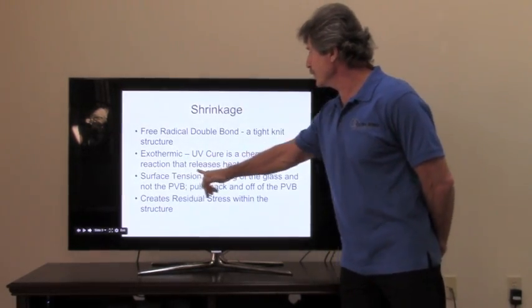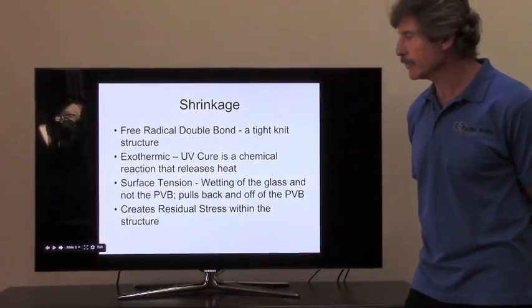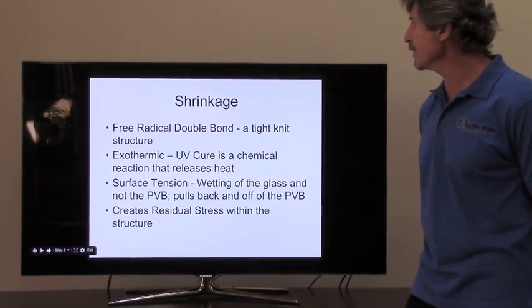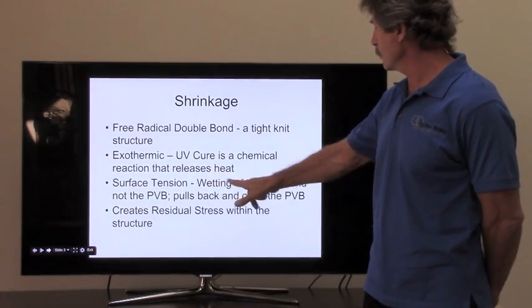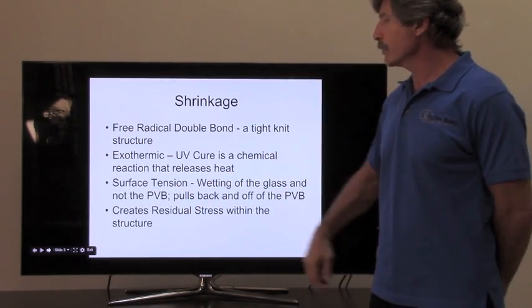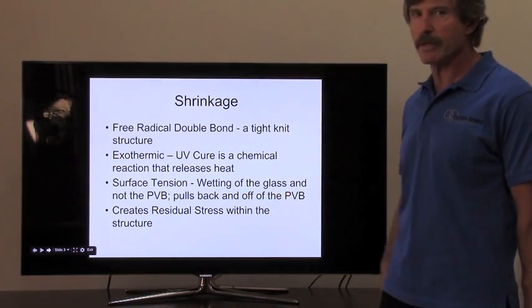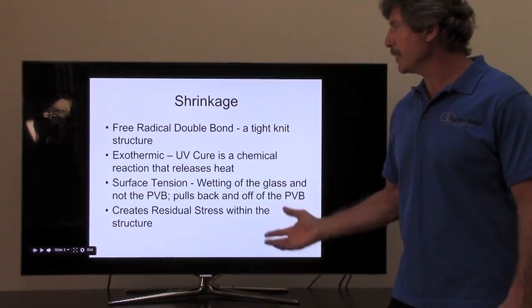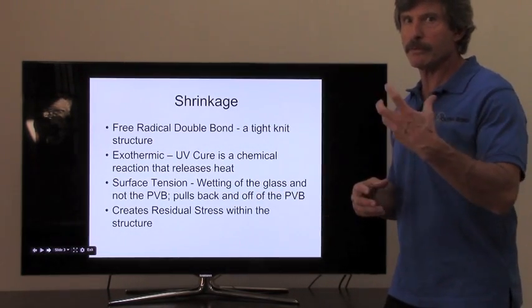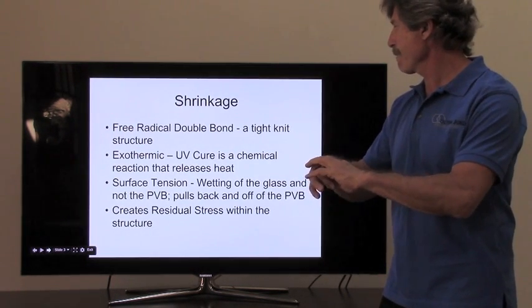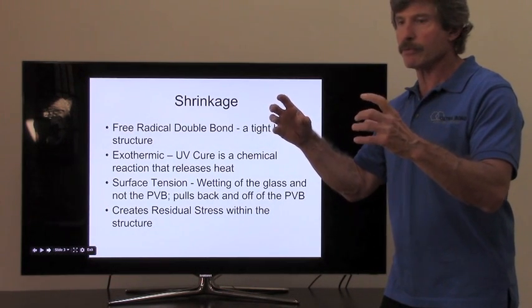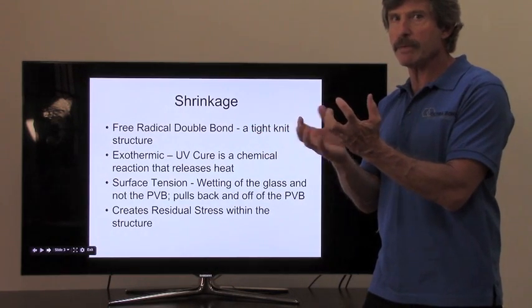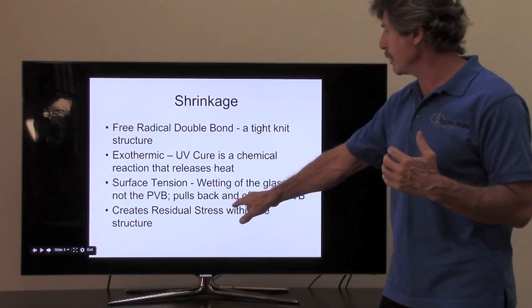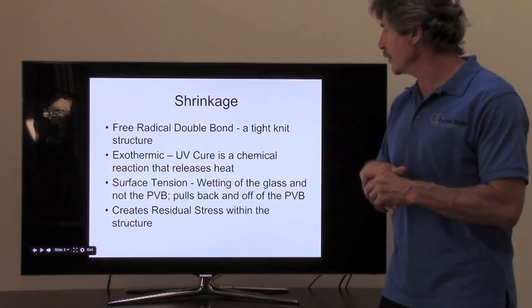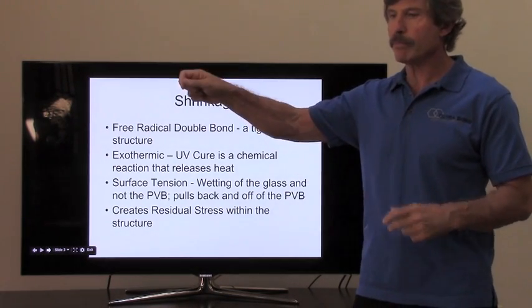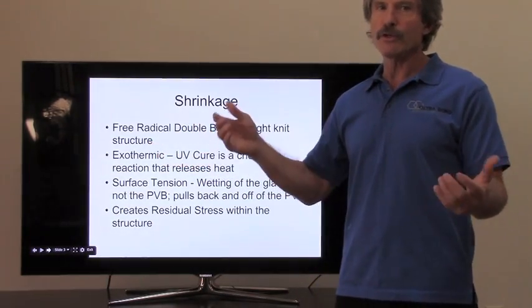And then there's another thing called surface tension, which I was covering earlier, and this comes into play because, again, we have two substrates. We have glass and we have PVB. And these windshield repair resins wet the glass and not the PVB. So that means when you go to cure, it will pull back and off of the PVB. When you hit the resin with UV light, those molecules are going to bond and link to the glass, and they're going to link to each other. So they're going to pull up and start cross-linking, and they're going to pull off of the PVB because they have no chemical molecular bond to the PVB, because the PVB is low energy. So you might see that if you fix a crack and you dump low viscosity resin in a long crack, when you go to cure it, you can see this.